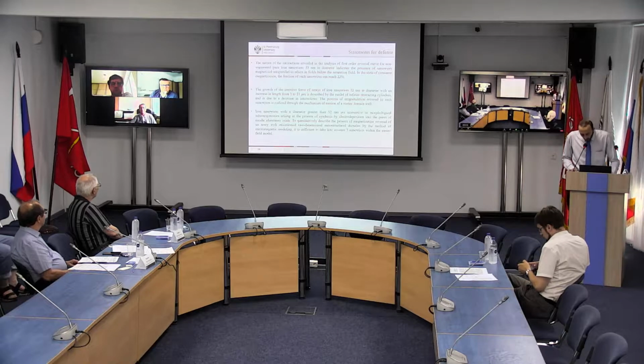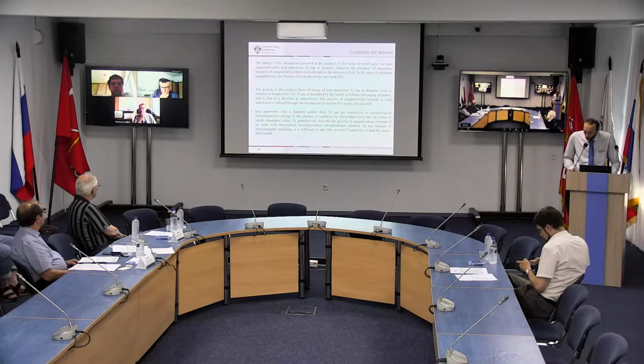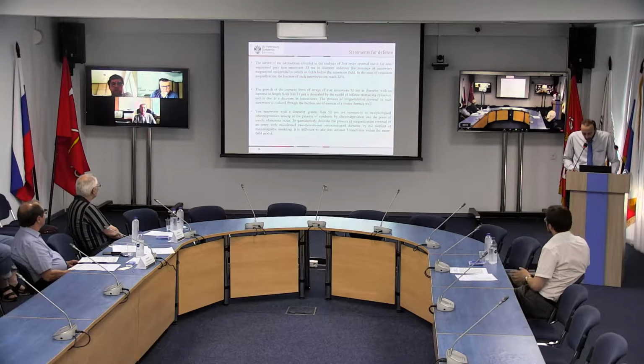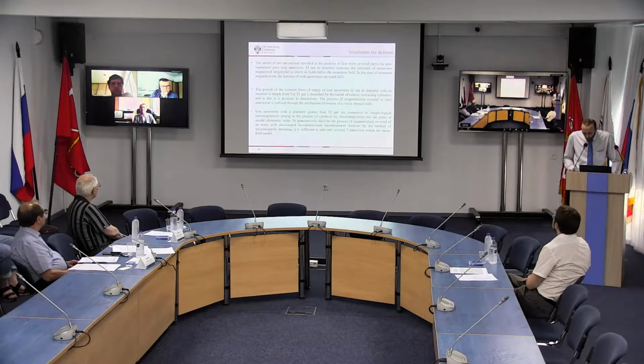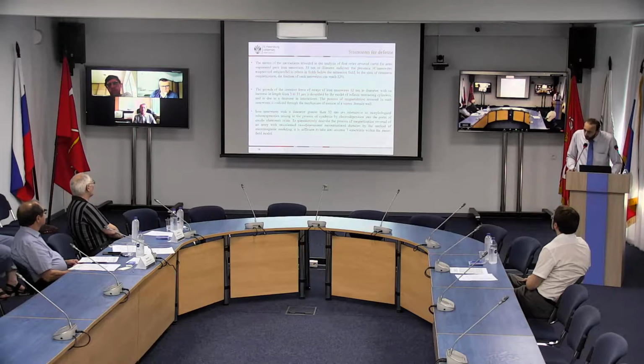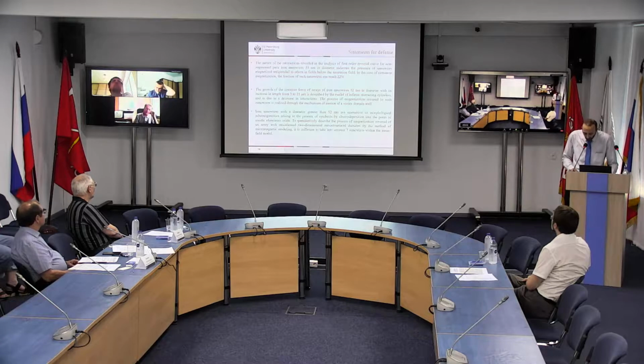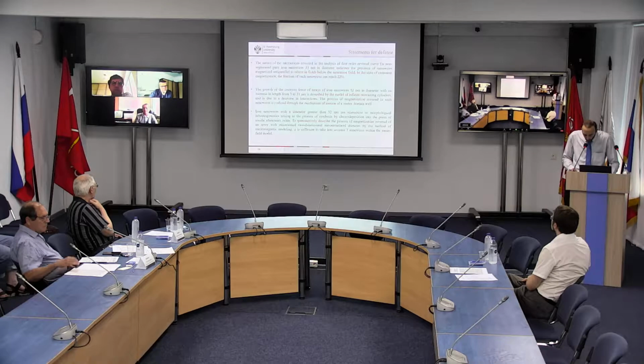Second point: the growth of coercive force of an array of iron nanowires, 52 nanometers in diameter, with an increase in length from 3 to 21 micrometers, is described by the model of infinite interacting cylinders and is due to a decrease in interactions. The process of magnetization reversal in such nanowires is realized through the mechanism of motion of a vortex domain wall. The last point: iron nanowires with a diameter greater than 52 nanometers are insensitive to morphological inhomogeneities arising in the process of synthesis by electrodeposition into the pores of anodic aluminum oxide.